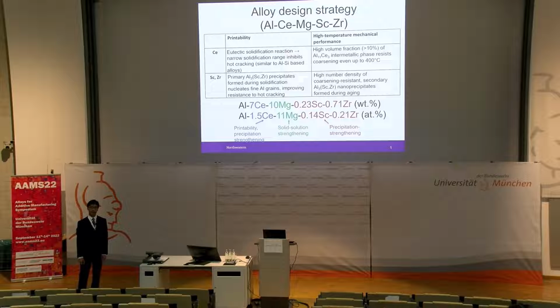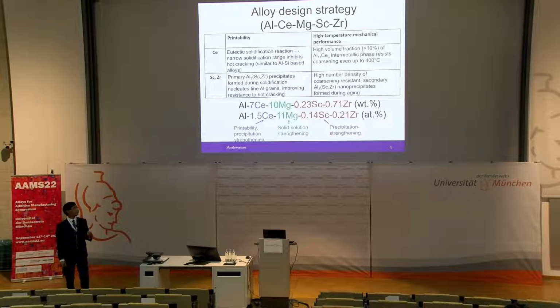And one reason for that is it exhibits this eutectic solidification reaction during cooling, where you form this aluminum and aluminum-11-cerium-3 phase at the same time. And this narrow solidification range inhibits hot cracking. This is quite similar to aluminum-silicon-based alloys, but the key difference is that this aluminum-11-cerium-3 phase is very resistant to coarsening due to the low diffusivity of cerium in the aluminum matrix. This enables these eutectic aluminum-cerium alloys to maintain their strengths at temperatures where aluminum-silicon alloys are becoming weakened.